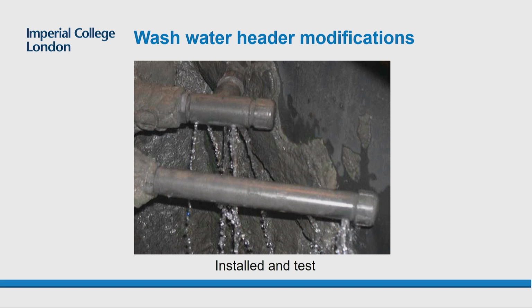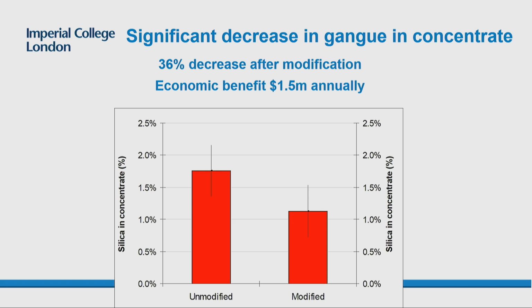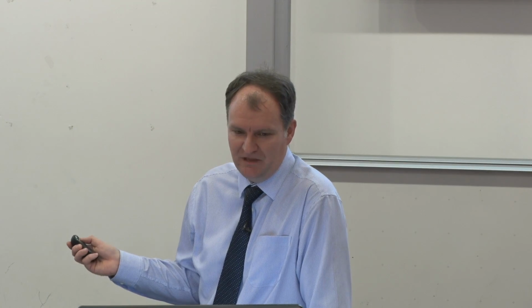But when we actually performed tests with these modifications, they found about a 36% drop in the amount of silica they were pulling over. So this had, at the time, about a $1.5 million change in their economic performance. And that's just from drilling a few extra holes and putting in a little bit of extra piping.